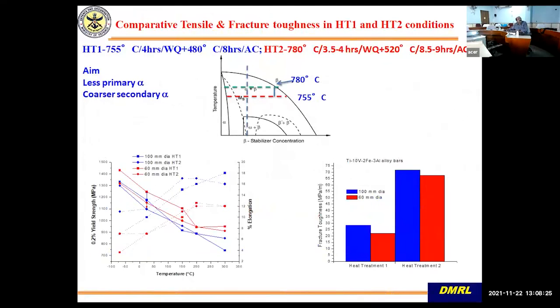And nonetheless, it was done by changing the solution treatment and aging temperature, because you are changing the primary alpha volume content, and thereby when you age, you are increasing the secondary alpha precipitation, and you can see the jump in fracture toughness which we could get. Here I am showing you the plot of different dias of the material, 60mm dia, 100mm dia, but I am not going into that, but that was also achieved by changing the heat treatment solution.